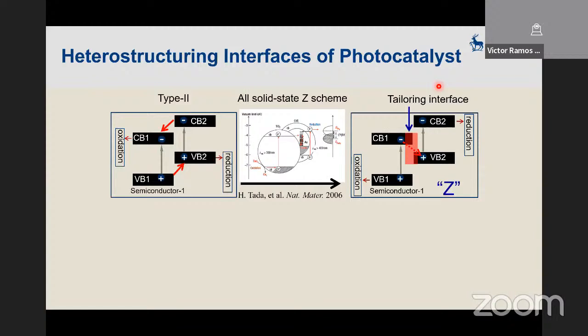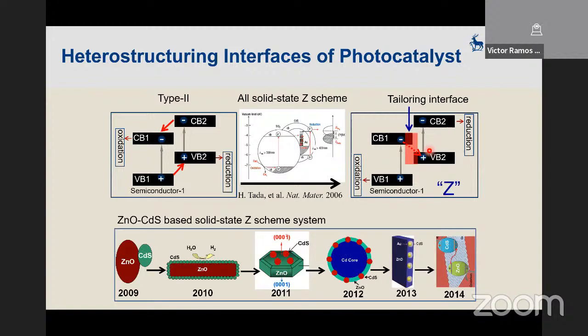Okay, so we have done some work in this area, trying to make a heterostructure at the interface of two different types of semiconductor, for example, zinc oxide and cadmium sulfide. So this is an all solid state Z scheme. So you can actually inject electrons into the conduction band, and eventually you have a better interface between two semiconductors, so that you can have a good match in terms of the energy band, so that you can maximize the efficiency.